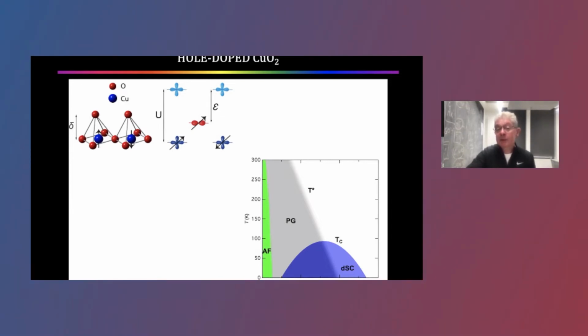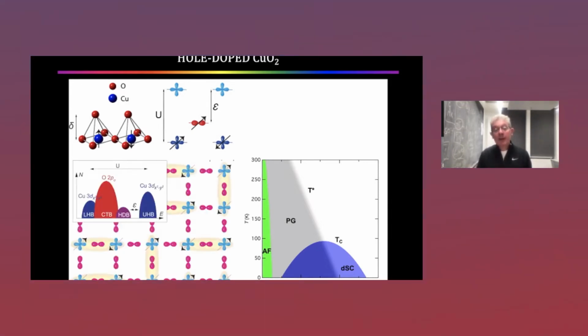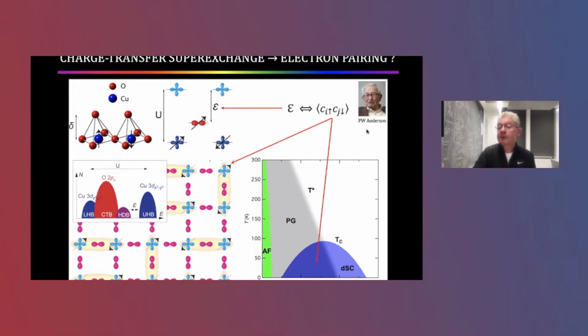Now, high Tc superconductivity. The band structure can't be changed much by adding 5%, 10% of holes. It'll be approximately the same, but maybe a new hole-doped band, sometimes called the Zhang-Rice band, would appear at the top of the oxygen band. And we know it's a superconductor. So Phil Anderson, God rest his soul, in 1987 proposed that what happens is that you destroy the long-range antiferromagnetism, but you keep the superexchange interaction. The superexchange interaction now forms singlet pairs, and they condense to make a high temperature superconductor.